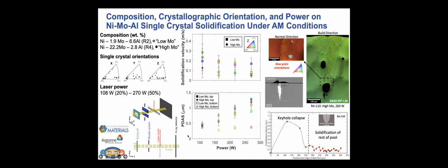Another thing we can look at is primary dendrite arm spacing, again, the length scale of the solidification structure, versus power, and some interesting things emerge out of this. We can see in particular for the high moly alloy composition at the bottom of the melt pool, as power increases, we actually tend to see more refined microstructures toward the bottom of the melt pool. Why is this? When we go to higher power conditions, we tend to go from a well-behaved melt pool scenario to a keyholing regime.